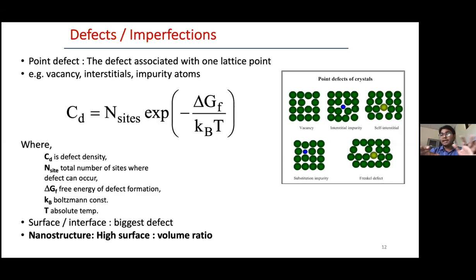So particularly, I would like to mention here the surface. We have said that anything which is missing from its position is a defect, and you can imagine the translational symmetry of the crystal is basically breaking at the surface. So beyond that, the crystal doesn't exist. So that is again the biggest defect in this system. So surfaces and interfaces are again among the biggest defects in the system. And naturally, when you are going into smaller and smaller dimensions of the materials, you are essentially increasing the surface, you are increasing the defects, you are increasing the defects that can actually participate in various things.